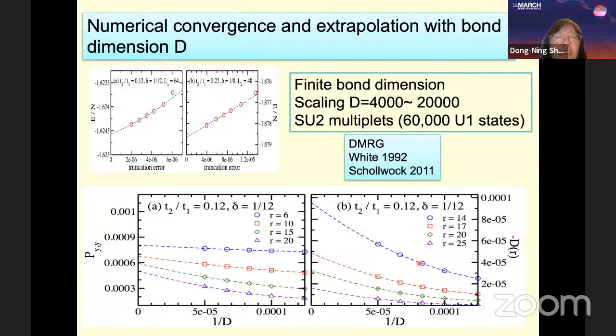As I already mentioned, the bond dimension we use for DMRG simulation is important. If we keep increasing the bond dimension, the truncation becomes smaller, and we can extrapolate the accurate energy of the ground state through extrapolation with truncation error. We can also do extrapolation with 1 over m, 1 over D, where D is the bond dimension, so when D goes to infinity we obtain the results at infinite bond dimension.